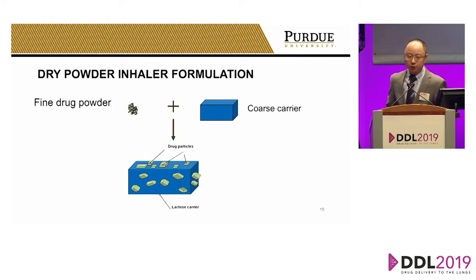One of the strategies to deal with this for low dose drugs is you can blend that with coarse carrier, in most cases lactose, and form what we call ordered mixtures. However, there are still some problems with this kind of formulation because, number one, for high dose drugs like antibiotics, we don't want to use a lot of these excipients. Number two, in some cases the drug sticks to the carrier too strongly and they cannot separate during inhalation. So it causes low efficiency of your formulation and device.